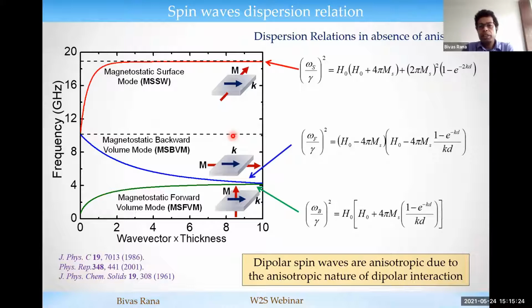So basically, there are three basic spin wave modes we always discuss for our experiments. That depends upon how the magnetization is oriented with respect to the direction of spin wave propagation. For example, if both of them are in the plane of the film but perpendicular to each other, we call that the magnetostatic surface mode. Basically, the spin wave propagates at the surface of the waveguide, and this is its dispersion relation. If they are parallel to each other, then we call this the magnetostatic backward volume mode, because this propagates through the overall volume of the waveguide. And this is its dispersion relation. The third one is the forward volume spin wave. It happens when the magnetization is aligned in the out-of-plane direction of the field. So this is all about the spin wave dispersion relation.